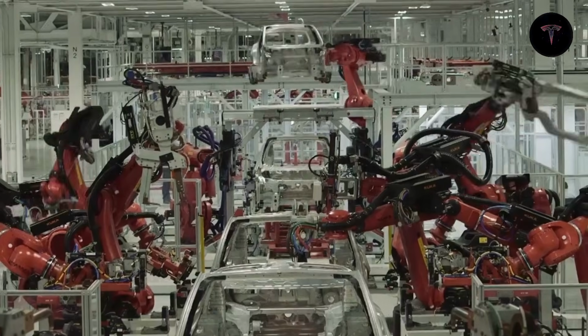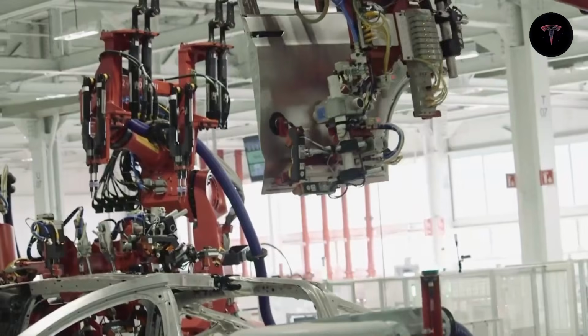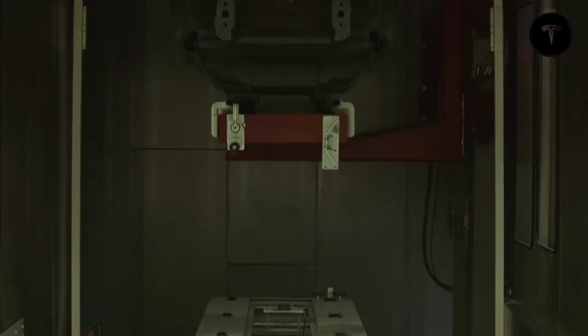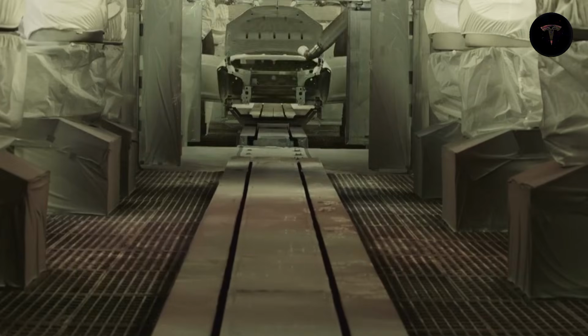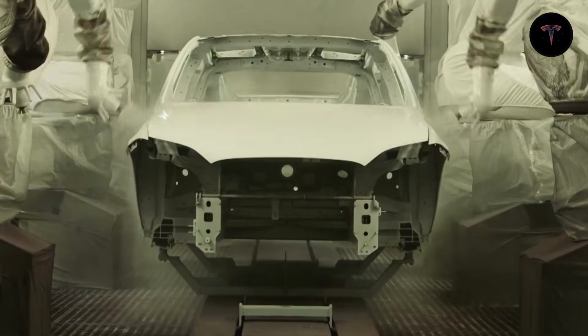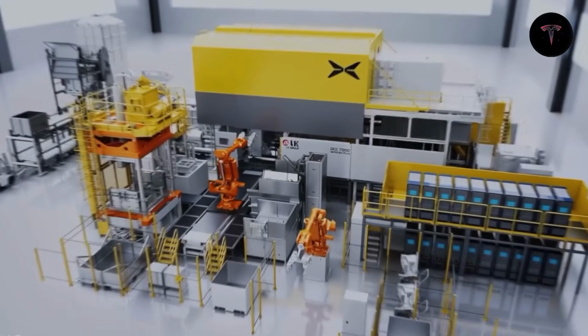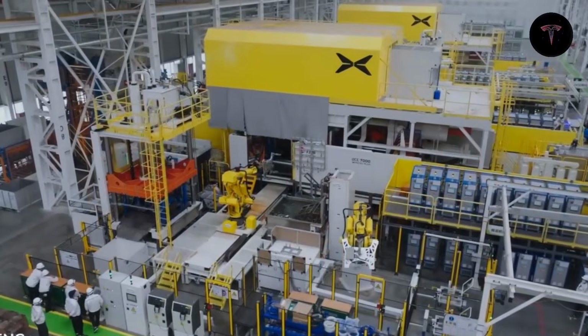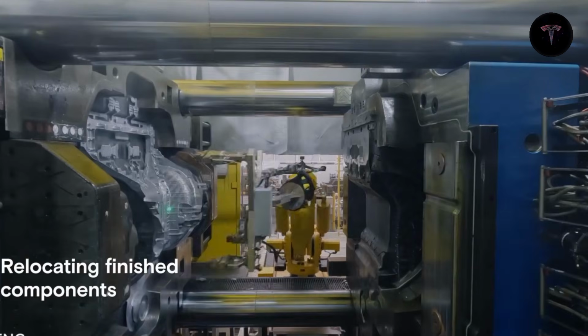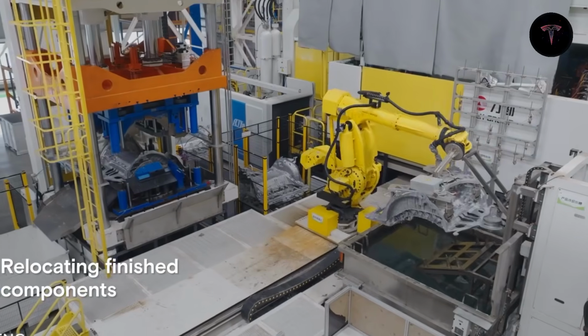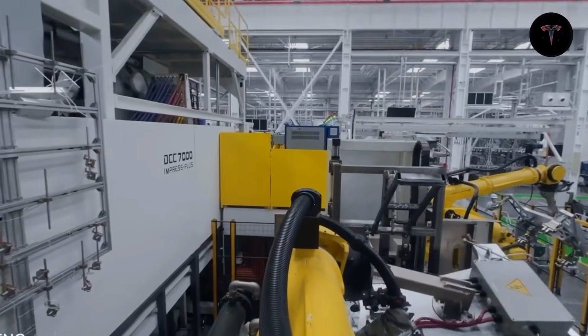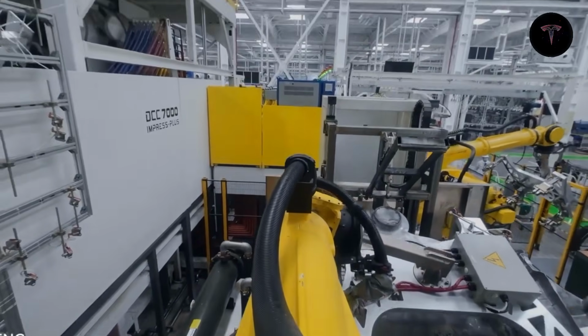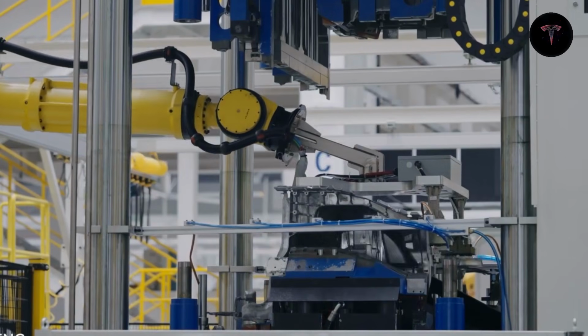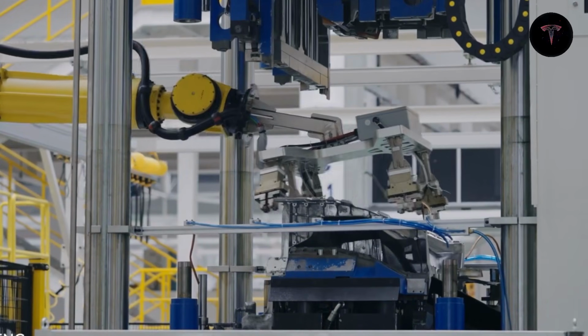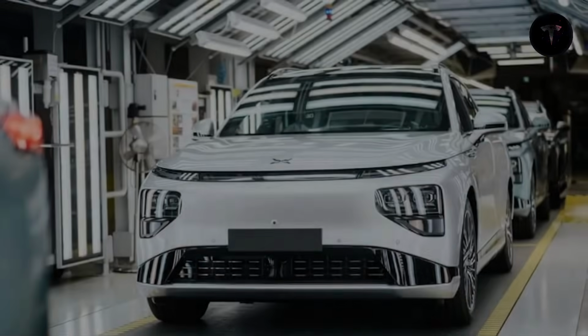Before each casting cycle, a robotic arm sprays approximately 35 milliliters of soybean oil across the mold surface as a release agent, a detail that sounds almost domestic, but is precisely calibrated to allow the finished part to separate cleanly without contaminating the next shot. A vacuum is drawn in the mold cavity to remove trapped air before the aluminum is introduced. Residual air causes porosity in the finished casting, which weakens the part structurally.